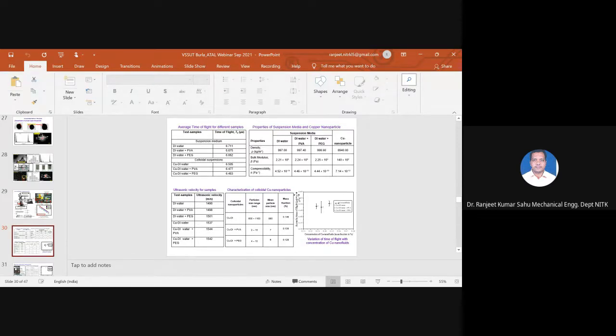Okay, and this is one figure which shows the variation of the time of flight with concentration of copper nanofluids. How does the time of flight vary? You see, this one represents the time of flight for copper particles dispersed in DI water. Similarly 2 and 3 are for copper particles in PBA and PEG solution. Each time of flight is plotted with an error bar, which shows the standard deviation of data from the mean value, when the probe is displaced consistently in the beaker. Here the time of flight for copper particles dispersed in DI water is found to be more as compared to the PBA and PEG solution.